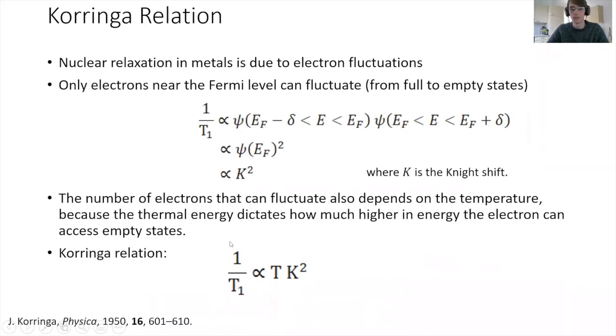Without going into too much detail here, the Korringa relation tells us what relaxation we should expect in metals, and it turns out that this is proportional to the Knight shift squared and is linear with temperature. So this is a really good way of testing whether you actually have a Knight shift or not: look for a linear temperature dependence of the relaxation. And often in metals, this is the mechanism that dominates. It's to do with the metallic electrons fluctuating, spin up, spin down, very rapidly, and that's what induces this nuclear relaxation, if that answers your question.